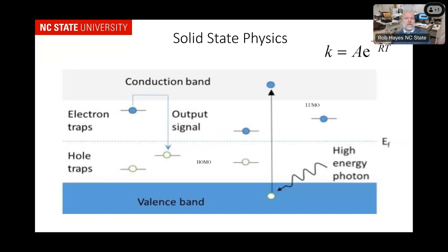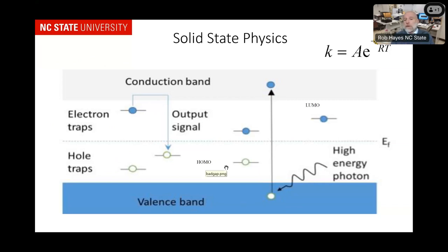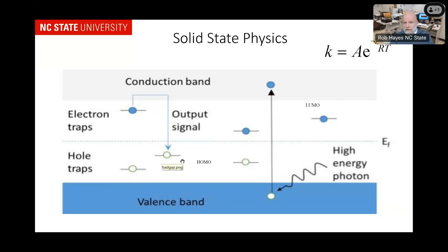These become sites where, when I expose something to ionizing radiation, I can either remove an electron from one or trap one of the ionized electrons at one of those defect sites. If I expose something to ionizing radiation, I take an electron from the valence band and put it up to the conduction band. It then has a certain probability of diffusing into one of these LUMO states, and I trap an electron there. Likewise, the hole can migrate into one of these HOMO states, and I trap a hole there.